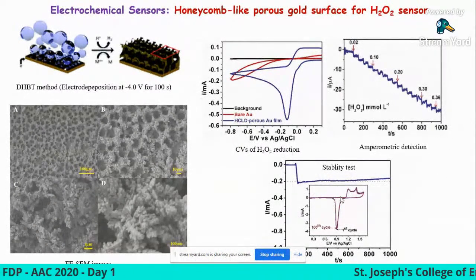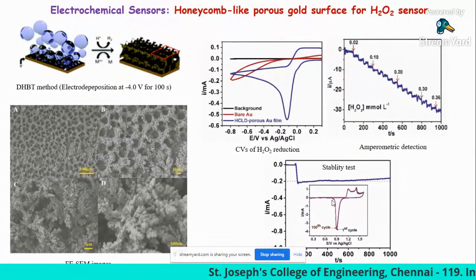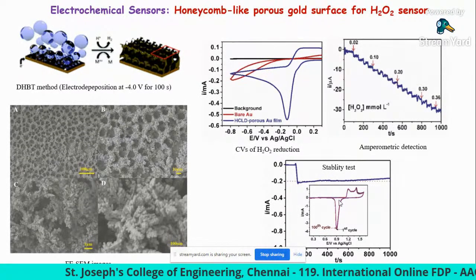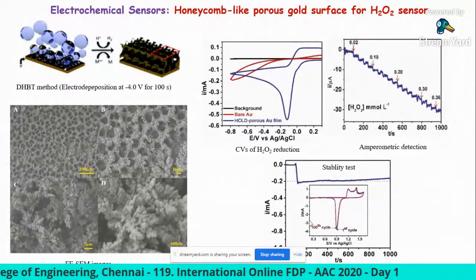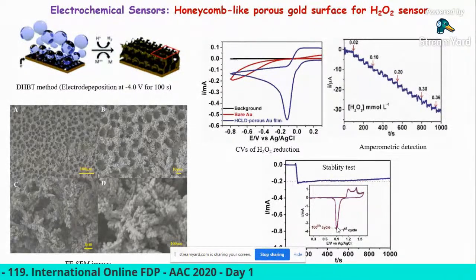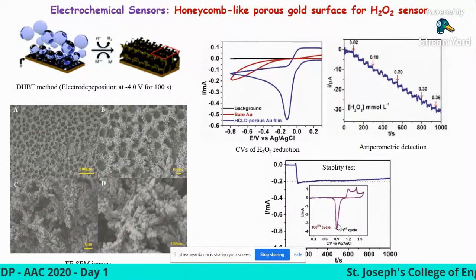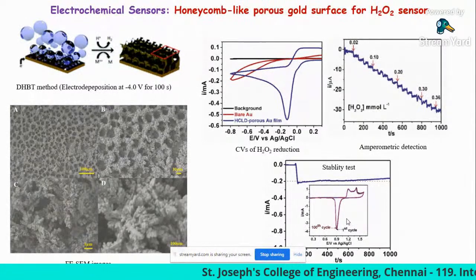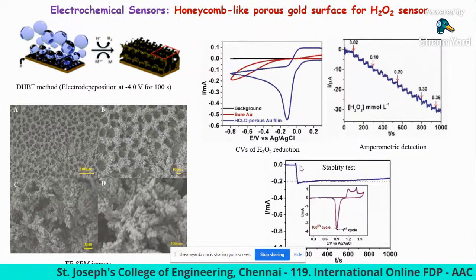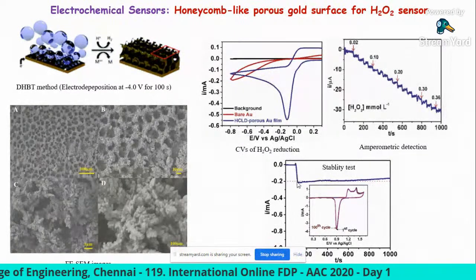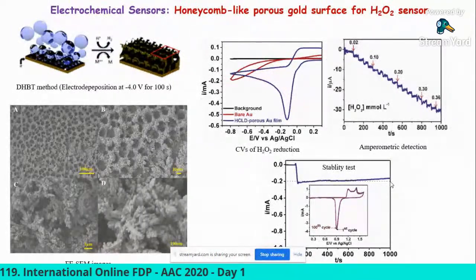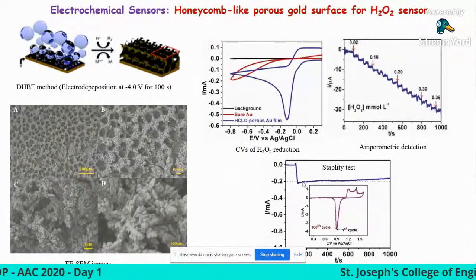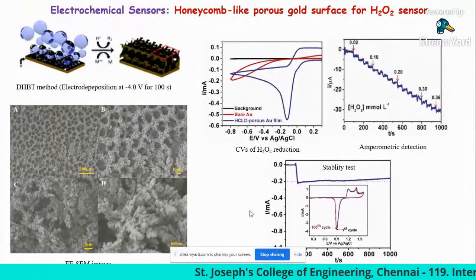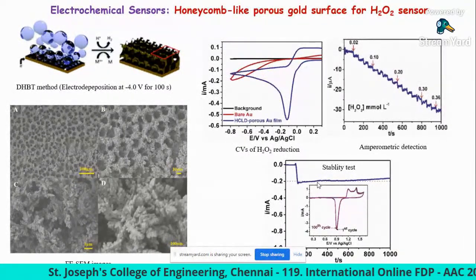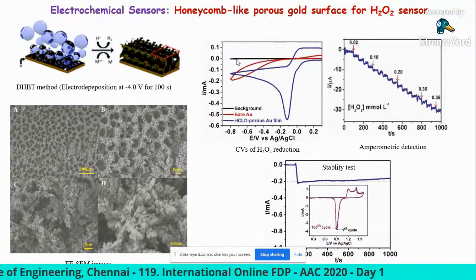And these are the stability measurements, where we studied the stability of the electrode in two ways. Here you can see the electrode continuously cycled for 100 cycles. Even then the gold oxide reduction current has not decreased much, which clearly indicates the fabricated electrode is highly stable. And then with hydrogen peroxide, when you add hydrogen peroxide, the current signal increases. Then we leave it for 1000 seconds, and the current signal is almost stable. So this data shows the response to hydrogen peroxide is highly stable on these nanoporous gold surfaces.